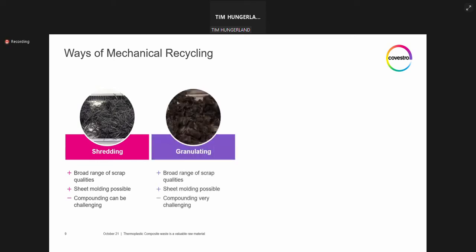Another process we have looked into is to granulate the composite waste. And this process ideally results in a sort of compacted scrap intermediate with a reduced amount of loose fibers. Similar to the shredding process, a broad range of waste qualities can be used, and sheet molding with the granulate is equally possible. However, depending on the degree of compaction, using this type of granulate can be rather challenging to use in compounding due to the limited flowability of the material. You might need to add some amounts of fresh polymer, for example, as sort of glue to improve this processability.